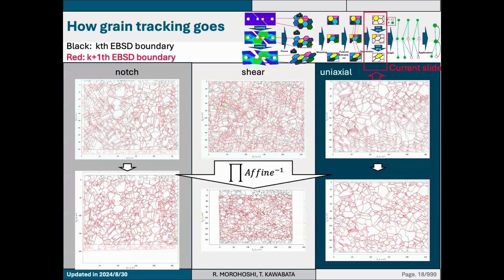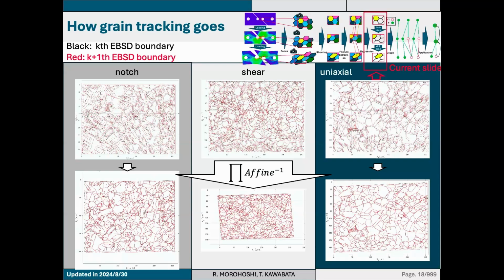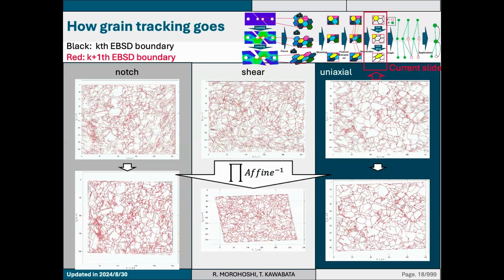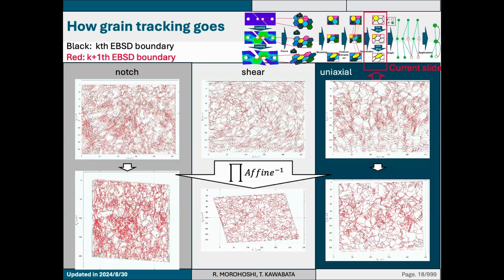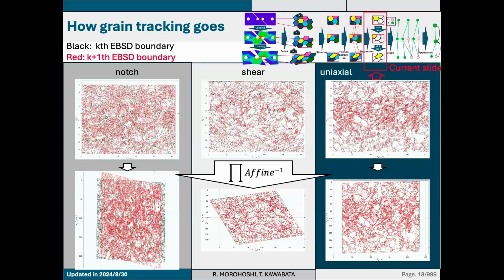These are the movies about the overlay of the grain boundaries. If the affine regression is precise enough, the original coordinates of any grains at any load can be calculated through the inverse of the accumulated affine transformation matrices. And these are the movies after applying it. In other words, the grain keeps stationary after applying it if the affine regression is enough. So yeah, seemingly that's enough.